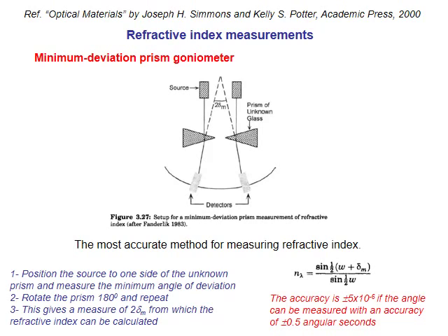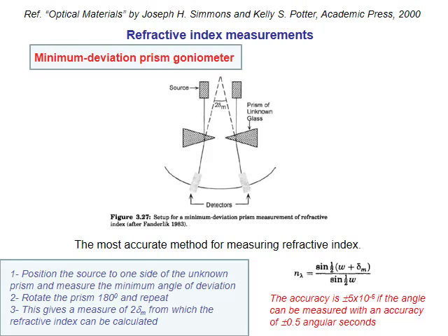This is the minimum deviation prism goniometer. It is the most accurate method for measuring refractive index. So we just need to position the source to one side of the unknown prism and measure the minimal angle of deviation. We rotate the prism 180 degrees and repeat the measure. This gives a measure of 2 times δm, from which the refractive index can be calculated.